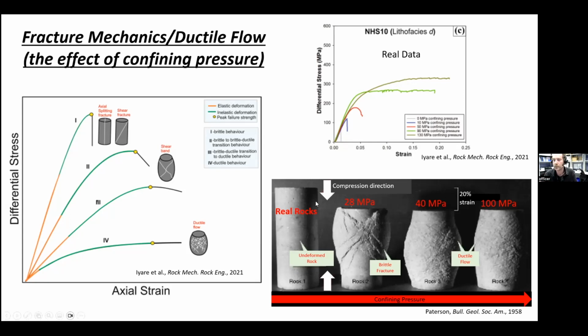And if you look at these, you have some real rocks on the bottom here, and at 28 MPa, you get brittle fracture. At 40 MPa, you get ductile flow, but you can sort of see a shear band forming here. But by 100 MPa, you just have purely distributed ductile flow. So as you increase pressure, it becomes harder and harder to fracture rocks.